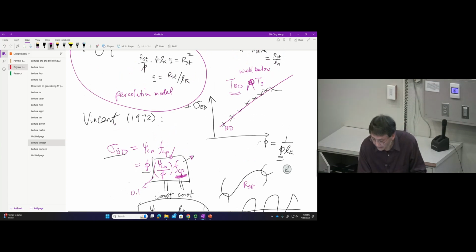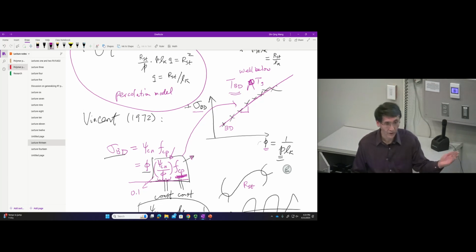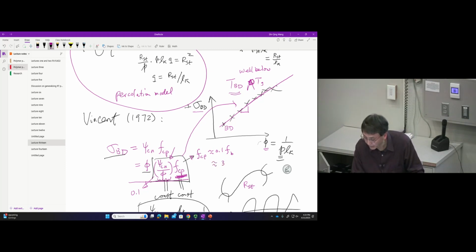So we have our theory, which is this expression. We have our data, which is this experimental information. You plot phi as a function of stress. This prefactor is this whole factor. And of course it is unknown because we're doing it at the scaling level. We cannot determine the so-called prefactor. But if you assume it's reasonable to think it's about a tenth, then it turns out this F is also about a tenth of the breaking force. In other words, for example, we estimate this to be about 0.3 nanonewtons, which is about a tenth of the breaking force.